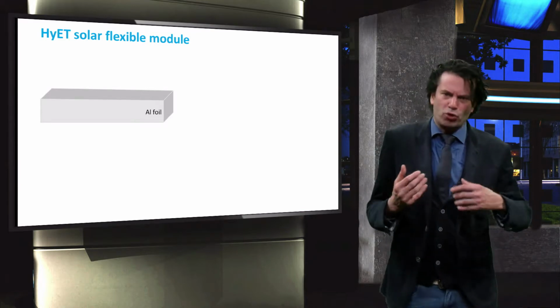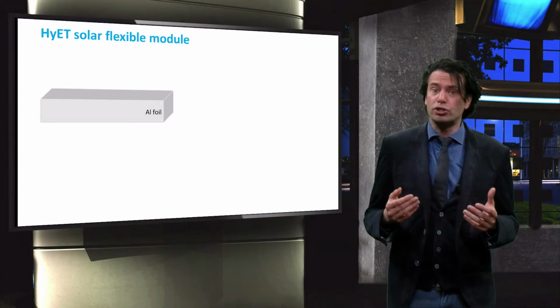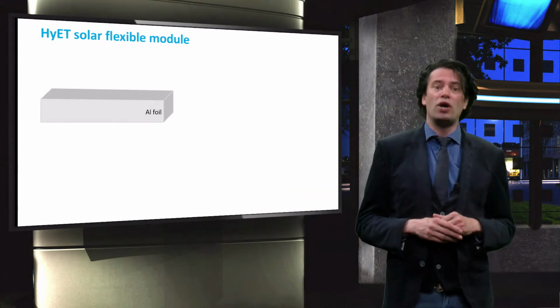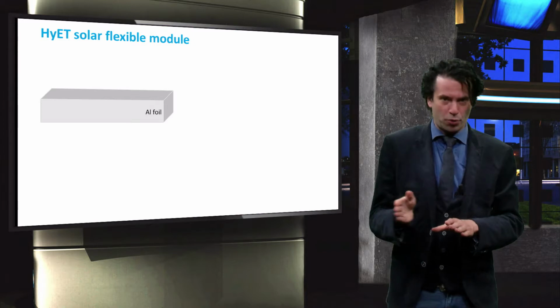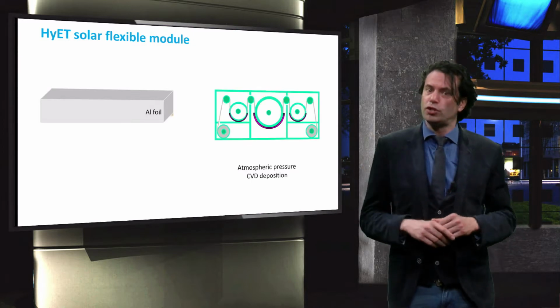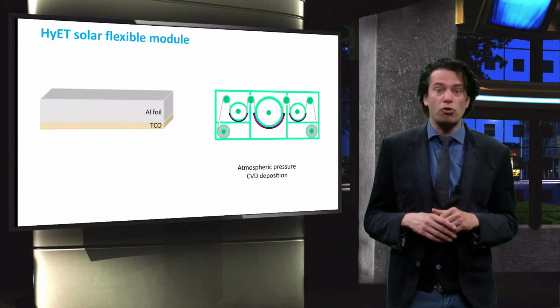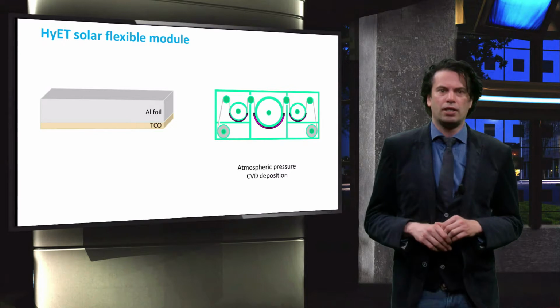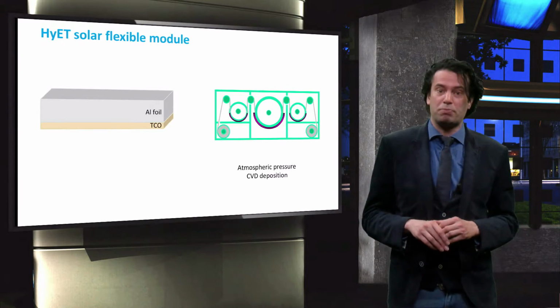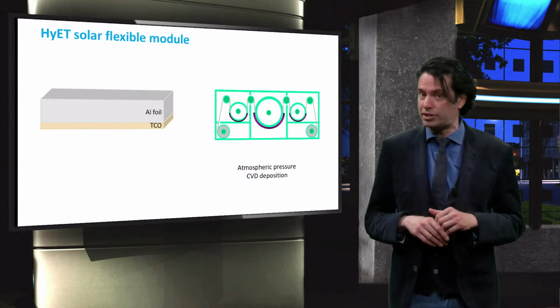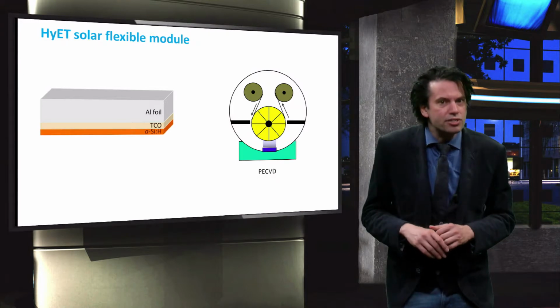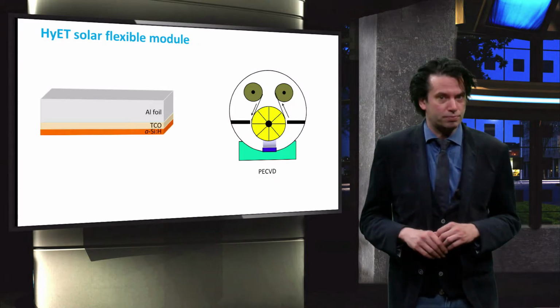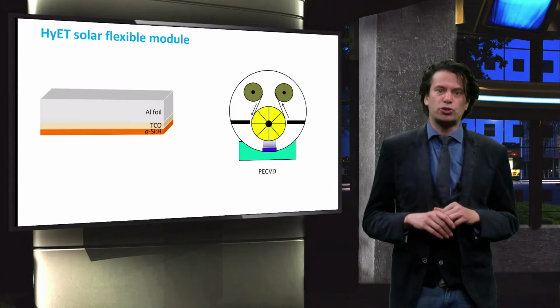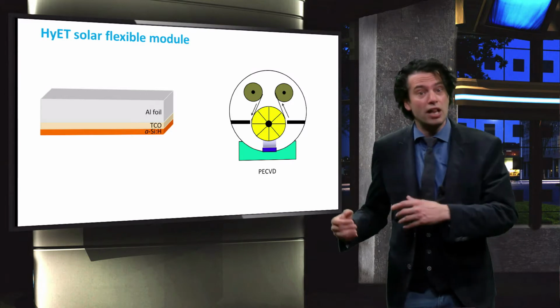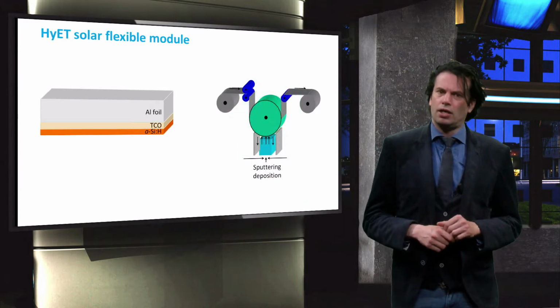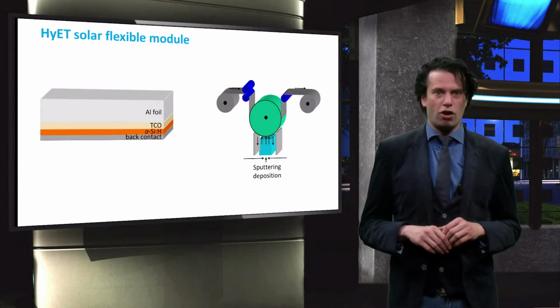Rather than the batch processing we just saw in the video, Hyet employs an innovative roll-to-roll production line where aluminium foil is transported through the different processing chambers. The first step involves the deposition of the fluorine-doped tin oxide TCO layer onto the aluminium substrate. This is done by atmospheric pressure chemical vapor deposition at a temperature of about 500 to 550 degrees Celsius. Then, the silicon layers are deposited using plasma-enhanced chemical vapor deposition. With this process, Hyet produces both single-junction amorphous silicon cells as well as micromorph tandem cells. The silicon deposition is followed by the sputtering deposition of the back contact.